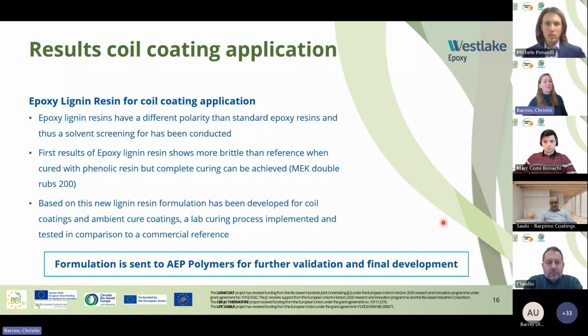So to come to the results of the coil coating applications, first of all, epoxy lignins do have different polarities, belonging to the process itself, also belonging to the glycidation reaction in comparison to standard epoxy resins. So we first need to start with the solvent screening to find the best suitable solvent. Out of that study, we could have the first results of epoxy lignin resins that unfortunately show a little more brittleness than the reference, cured with phenol epoxy resins. But by the use of an MEK double rub test, we could see that a complete curing can be achieved.